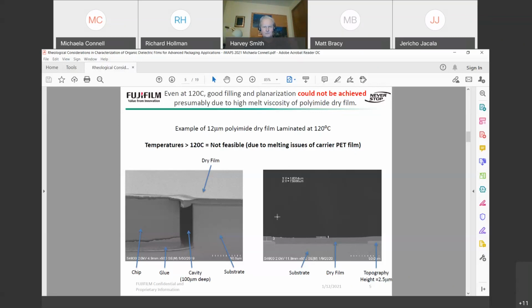And on the right, we have topography with a height of 2.5 micron. And even with 12 micron film, the dishing between the structures is 1.6 micron. In order to create flow with this polyimide dry film, it may be necessary to increase the lamination temperature even further. However, temperatures greater than 120 degrees Celsius are not feasible in this case due to melting issues of the carrier PET film.